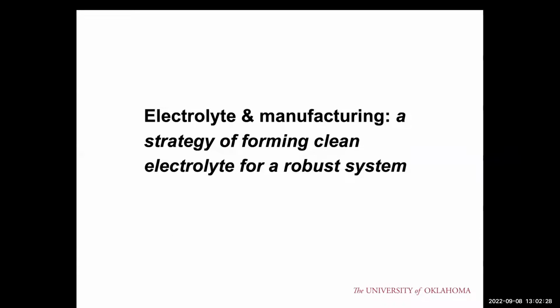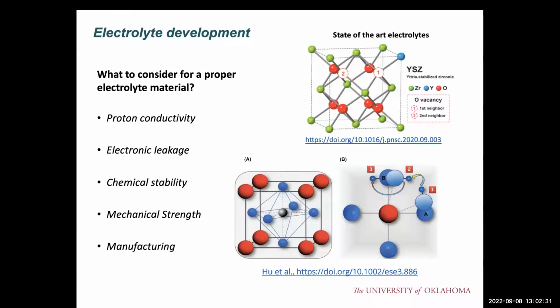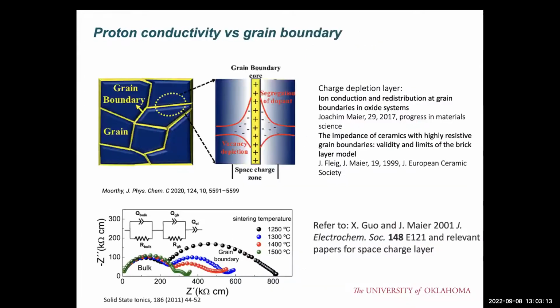The second piece of work is the electrolyte work. Typically for the oxide conducting, one is yttrium-doped zirconium oxide, which is an oxygen conducting electrolyte. Another is proton conducting, which is based on perovskite materials. For all of these electrolytes, we have some criteria for being considered as electrolyte materials: conductivity, electronic leakage, stability, mechanical strength, and also manufacturability. So we need to make a compromise across all the parameters, and eventually we can select the good materials.